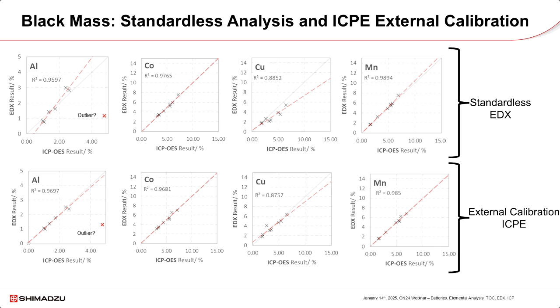The red dotted line is the regression in the graph between the EDX result and the ICP result. The gray line would represent a perfect correlation between the EDX and the ICP. On the bottom graph, the EDX results were calculated using the ICP data. In other words, the ICP was used to calibrate the EDX. We call this an external calibration using the ICPE.